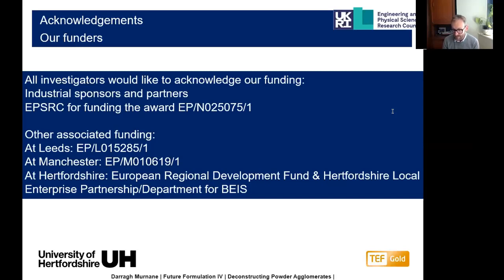We have worked, and Parmesh particularly has worked with Zeiss quite closely on this. It is proprietary technology, so I can't really talk very much yet about the way that it's worked, but it's using X-ray physics to identify differences between the materials. So we can now do that. There was a question around the scale at which we can pick out those differences. Well, we're able to identify individual particles down to about 2 microns within the microscale CT, and we can identify down to 200 nanometers within the nanoscale CT. So we do get an ability to study that right between the scale ranges which are important for inhalation, and we're able to use X-ray physics to identify different chemical species within the blend.